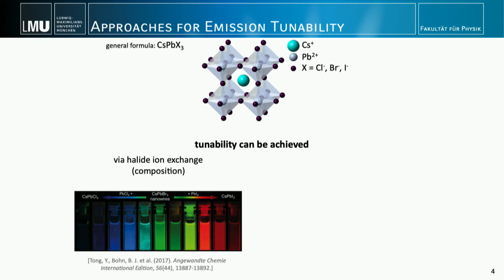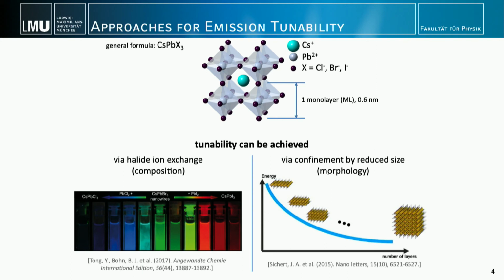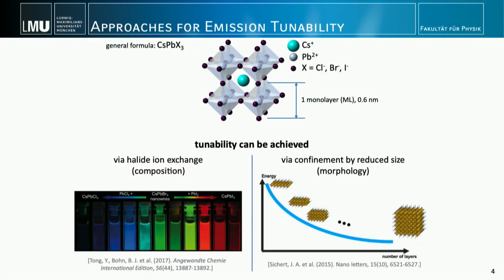So the second way to achieve tunability is via quantum confinement. So by reducing the crystal size, and we start with a cesium lead bromide crystal, which is in the green range, as you see on the left, and we simply make the crystals thinner and thinner. We start with a cube, and as we go thinner and thinner, it will end up being platelets of different thicknesses. And this can be done with such an accuracy that we really talk about monolayers of this crystal structure. You see in the top, one monolayer is only 0.6 nanometers, and we can achieve just multiples of that. For example, 2, 3, 4, and so on.